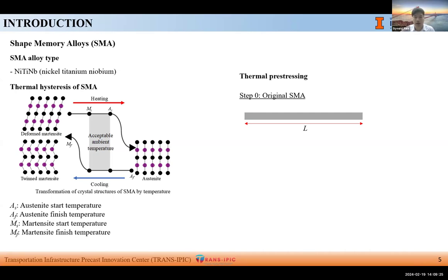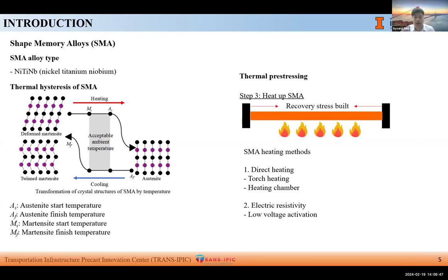Thermal pre-stressing is done by using the shape memory effect of SMA. SMA tries to recover its original shape when heated up beyond the austenite temperature. Using this feature, as shown in the animation, we pre-strain the SMA and anchor it. After that, by heating with direct heating or an electric method, as the SMA is fixed to the anchor, it cannot recover to its original shape and builds recovery stress. This confining or pre-stressing force is transferred to concrete, limiting cracks.